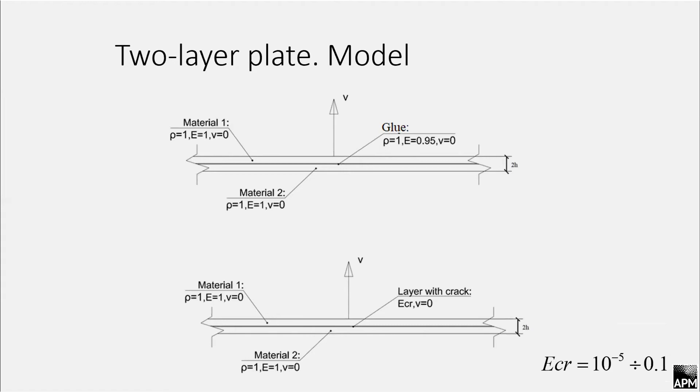When interfacial crack appears, deformation modulus of the glue layer equals values from 10^-5 to 0.1. By this, we can estimate the damage degree in case of non-destructive testing for some damaged elements, or the degree of healing for self-healing composites by varying the modulus of deformation for the glue layer.